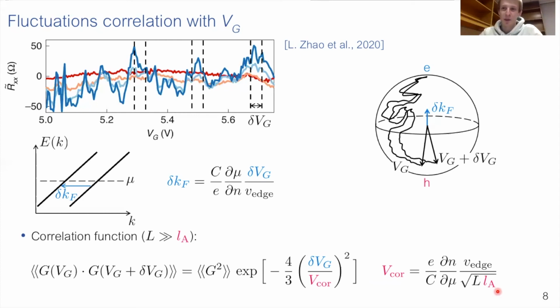And at first we were puzzled by this observation, but then we realized that something similar happens in nuclear magnetic resonance. There is a phenomenon called motional narrowing. So essentially, the width of the NMR line becomes more narrow if the spin is placed in a more stochastic magnetic field. So this is kind of neat physics that we uncovered in the correlations of the fluctuations.